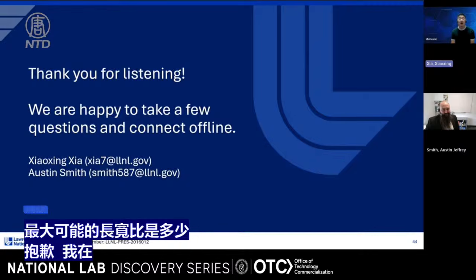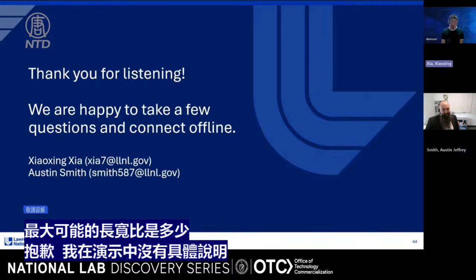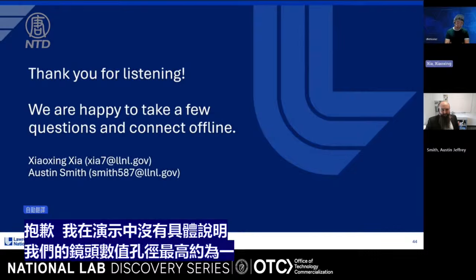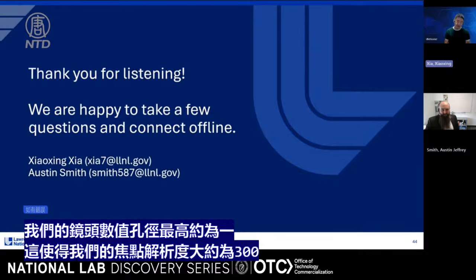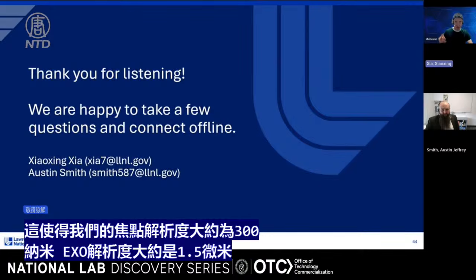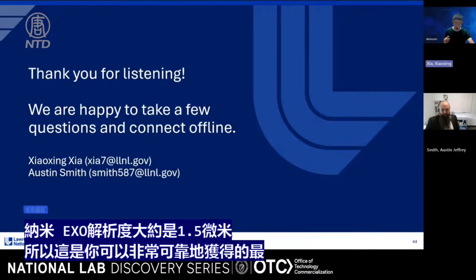Okay, so our diffraction, sorry, I didn't specify that in the presentation. Our lenses have a numerical aperture, the highest we do is about 1. That gives us a radial resolution of the focus spot of about 300 nanometers, and the axial resolution maybe about 1.5 micron. So that's the minimum diffraction limited resolution you can get very reliably.